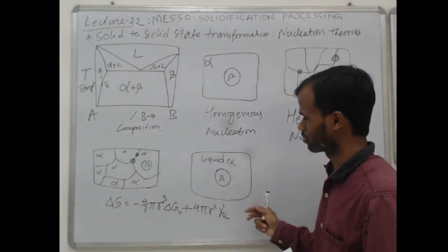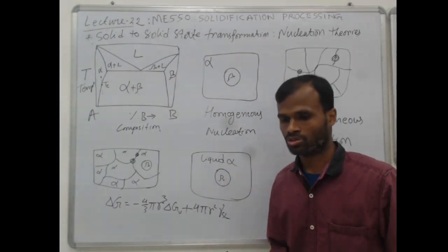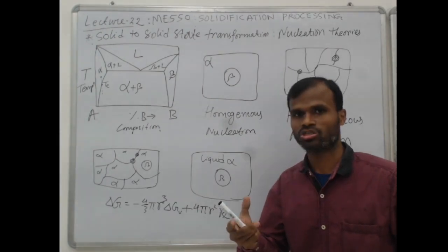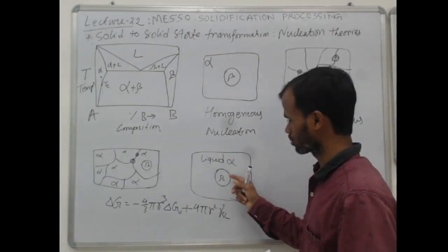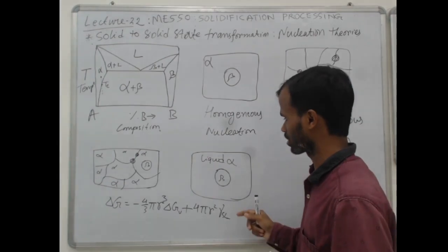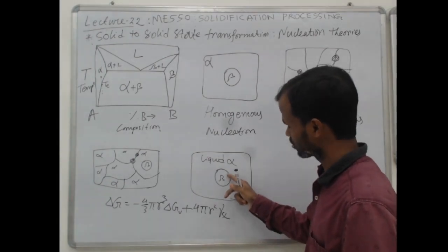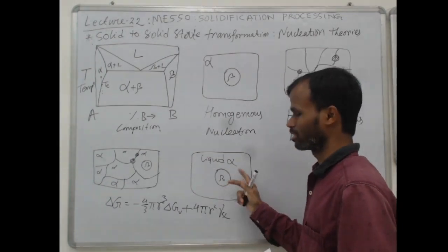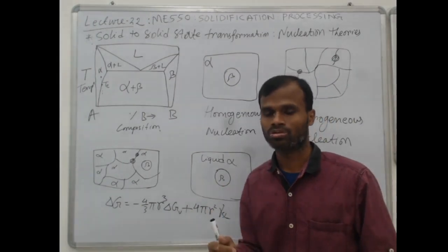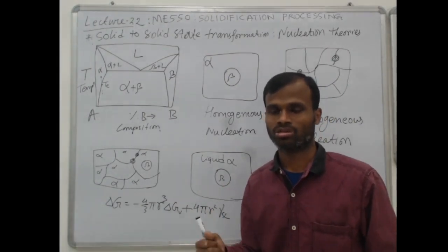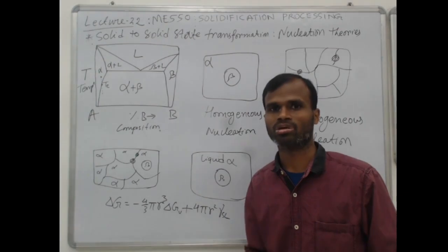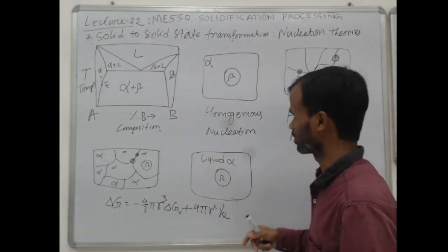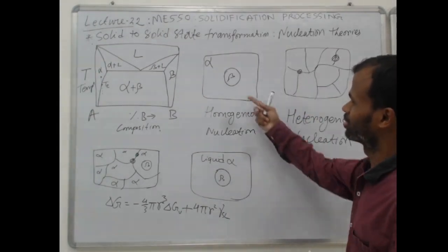If the density is not the same, their volume will be different, so there will be some expansion or contraction. Because of such expansion or contraction, this will apply some strain to the liquid, but the liquid is free to move. So there will be no strain actually, no resistance, and no development of stress. But if you consider a solid, now the moment